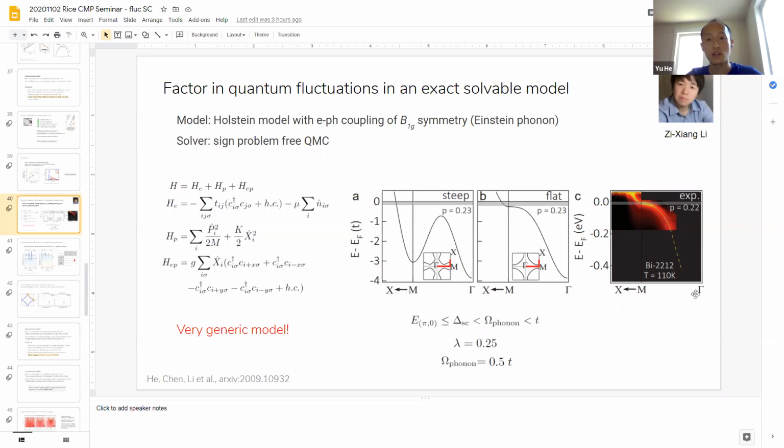So we are motivated to ask a question: in the case where only part of the momentum space is deformed to be very flat and shallow close to EF, can that actually give us enhanced pairing fluctuation? In the spirit of the BCS-BEC crossover, even though we clearly know it's not a BEC regime, it's a BCS regime. With that in mind, we can already have a physical intuition by looking at the Fermi velocity. In those partially flat shallow bands, the Fermi velocity is really, really low. So even if we were to just come from textbook BCS, that will give us a really, really short correlation length. And a shorter correlation length gives us a much smaller correlation volume, and thus a very small number of Cooper pairs, if overlapping at all, within that correlation volume. Therefore, there is an innate tendency to have stronger fluctuation, even just from arguing from the BCS picture.